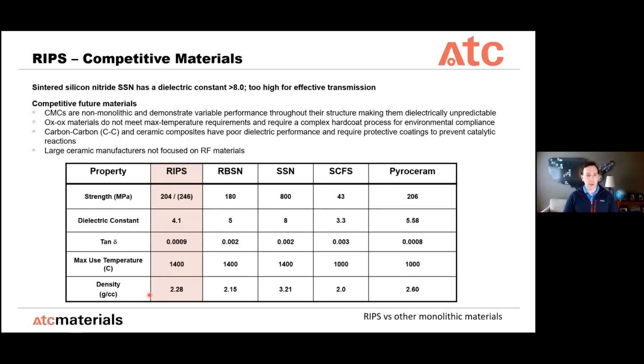Looking at some of the competition here. So this is us, RIPS in pink or red here, compared to a fully dense sintered silicon nitride. So strength is reduced significantly, but still shows enough to survive. Perhaps not as a leading edge, but certainly works well for the RF elements that are on any of these vehicles. But the key thing is our dielectric constant is half of a fully dense silicon nitride, which means that those sensors can operate effectively.